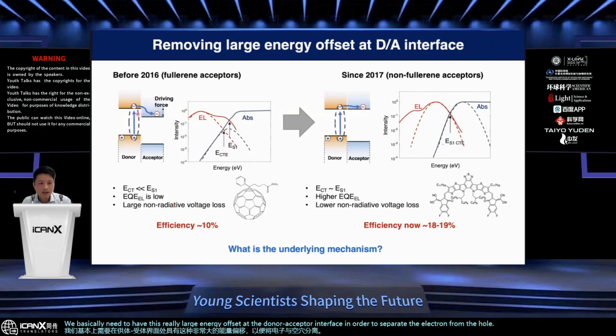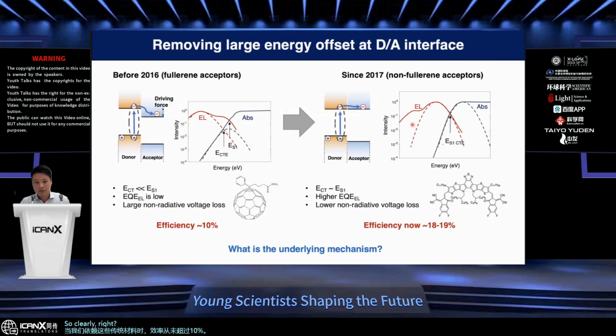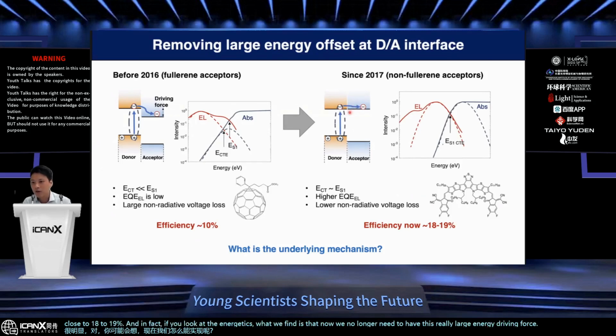And it is because of this reason, because we need to pay this energy deficit in order to separate the charges, that the efficiency has never been above 10% when we rely on these traditional materials. So clearly, you might be wondering, how come now we can achieve close to 18 to 19%? In fact, if you look at the energetics, what we find is that we no longer need this really large energy driving force at the interface in order to separate the electrons from the holes.